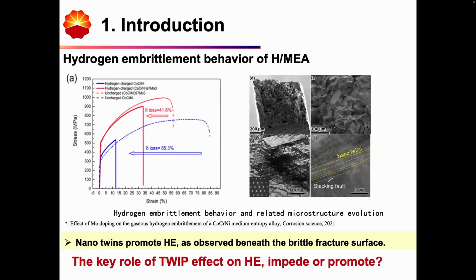On the contrary, if we change the hydrogen charging method from cathodic charging to gaseous hydrogen charging under 91 megapascal, we see different results, with an obvious decrease in the fracture strain of the medium entropy alloys. The fracture mode changed from ductile dimple fracture into intergranular fracture, and extensive nanotwins are observed beneath the intergranular fracture surface, promoting the initiation and propagation of brittle fractures.